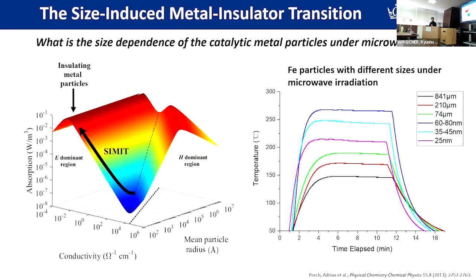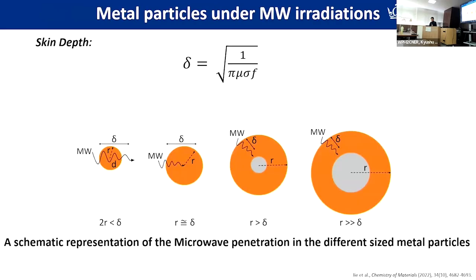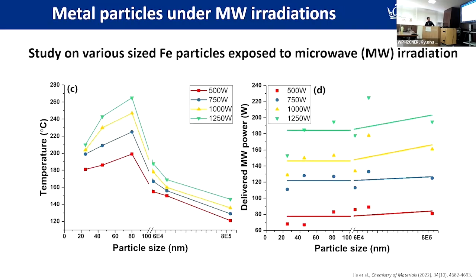So this again demonstrates how important the size of the metal particles is when we start to design and prepare our catalyst. This is a core, key point we need to consider. And one thing we also noticed, very interestingly, is that although we might say the smaller size is preferred in the microwave because it heats up well, if you see this diagram, you will see that is not so, because the smaller iron particles actually heat less than the larger iron particles.